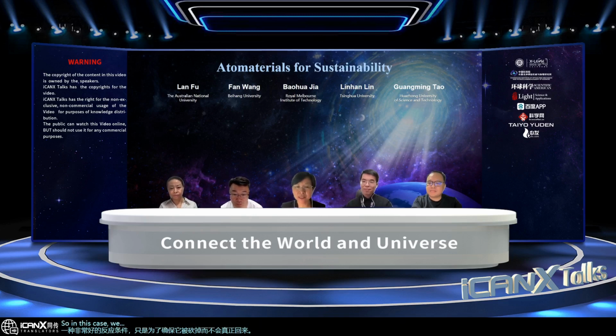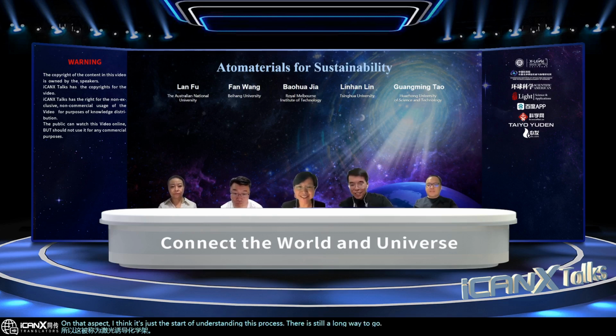So in this case, most of our reduction was using femtosecond laser. Femtosecond laser, you probably know, is a cool fabrication process compared to continuous laser or nanosecond. So the heat accumulation is much less. But we also noticed that using femtosecond laser, if you change your pulse oscillation or pulse shape, you are able to control the chemical bond to some extent. So this is called laser-induced chemical reaction. On that aspect, I think it's just the start of understanding this process. There's still a long way to go. Yes, I think you raised a very good question. Thank you.